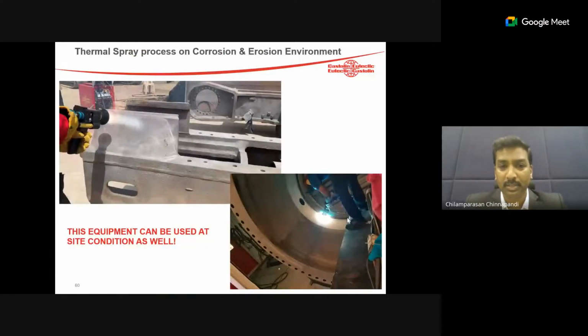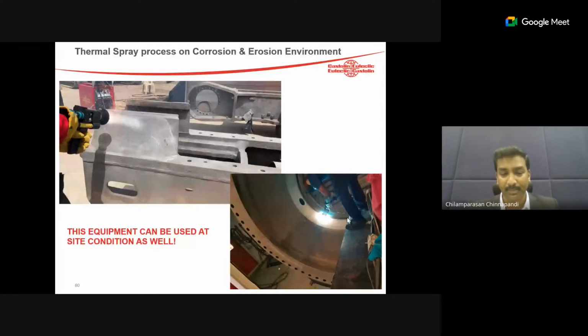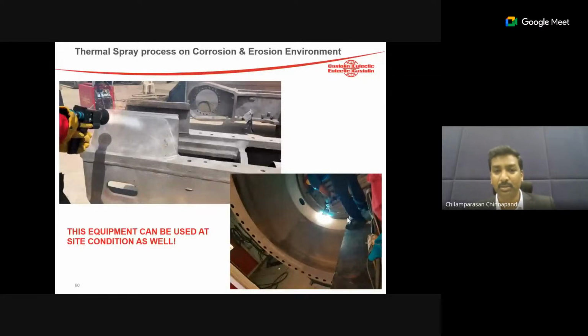And this process or this equipment can be used on atmospheric corrosion problems. If you're using normal corrosion paints in the market, it gets corroded again after 1 year or 6 months. If you want any kind of solution, we have very good solutions which will work as cathodic protection of the component, and we can spray aluminum, zinc, or different kinds of wires which can completely protect your structurals. That is atmospheric, and also any seawater inlet pump valve.